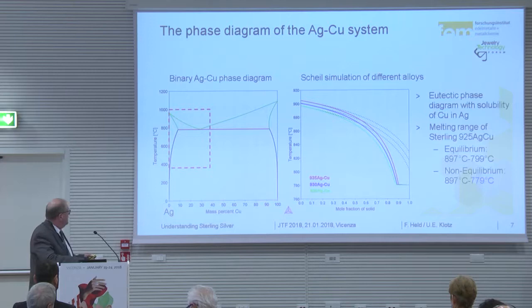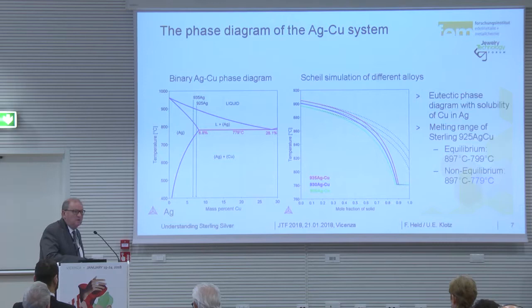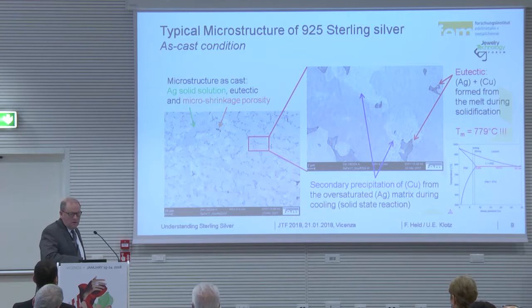We always talk about silver 925, but that's a hallmark. The silver used, for soldering and so on, depends. It could be 925, but it could also be 935, so we have this range here. That's a typical microstructure picture of sterling silver. We have solid solution here, the eutectic phase, and microshrinkage porosity here. Here is the same silver with eutectic phase, but no microshrinkage.